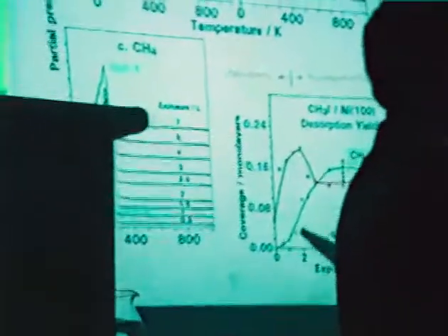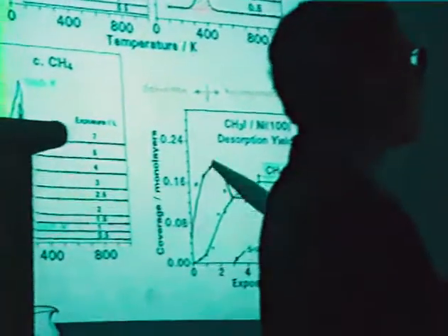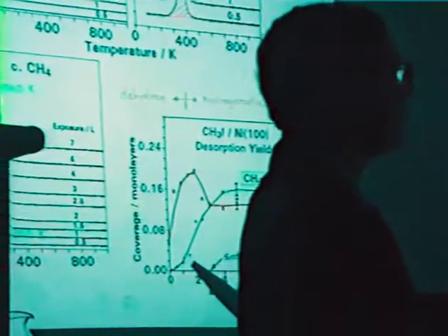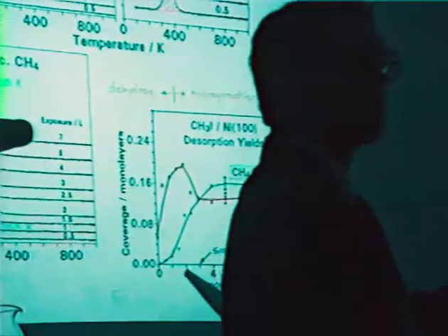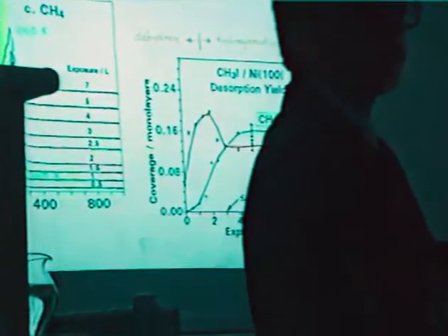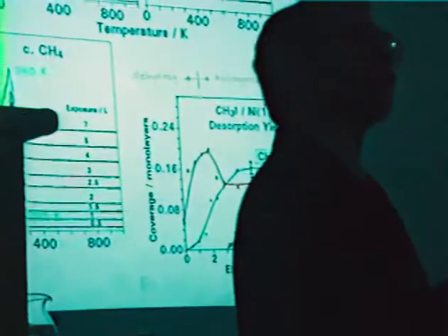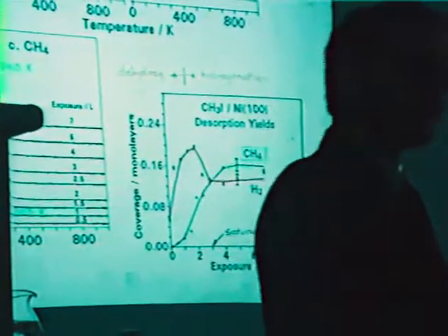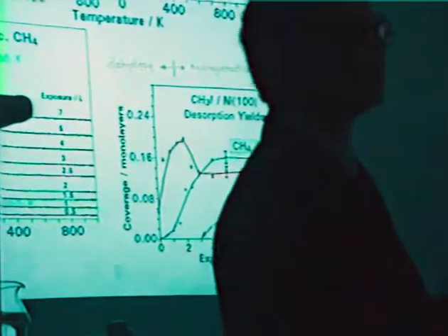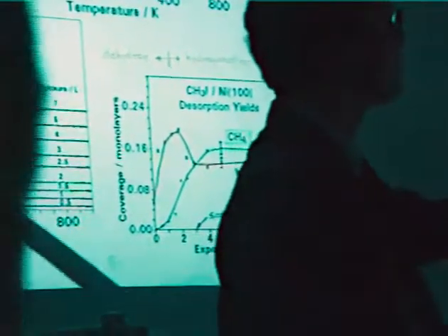Here we have the yields, and basically it illustrates one of the things I was saying. At low temperatures, you get a lot of hydrogen and almost no methane, but then at about half saturation, you get a threshold coverage where you get a lot of methane and less hydrogen from decomposition. So you have actually switched between having mostly dehydrogenation to having mostly hydrogenation. There is still the question about the formation of methane, how it takes place. And that's what I want to address next.